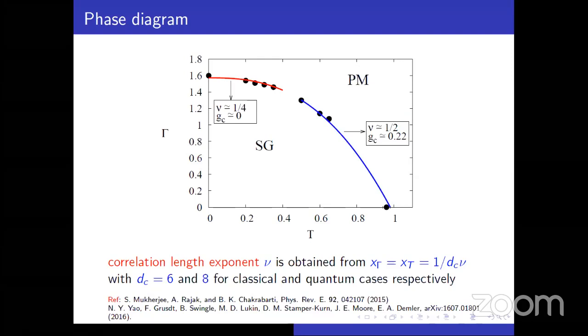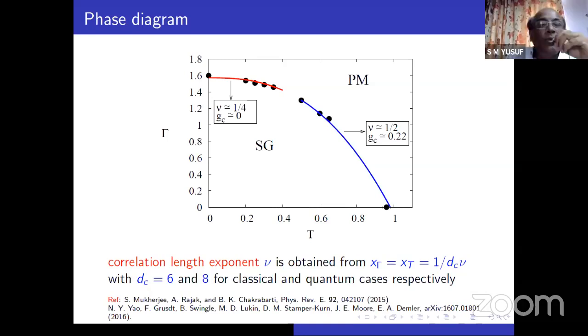Then you put it in a transverse field, whose amplitude is gamma, capital Gamma, coupled to sigma x. So it is not commuting. That will give me the tunneling from one eigenstate of sigma z to another eigenstate of sigma z. The whole thing is put in a temperature bath.